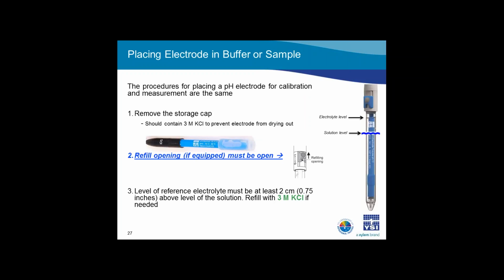When placing a sensor in either a buffer for calibration or a sample for measurement, make sure you first remove the storage cap from the tip of the sensor. The storage cap is provided for storing the electrode during shipment and long-term storage. I consider anything 3 weeks or longer to be long-term storage. For field probes, we'll talk about storage of lab probes shortly. The storage cap is filled with solution to keep the electrode from drying out and to slow the outflow of electrolyte. The solution used varies by manufacturer and electrode, but is usually KCl solution, buffer 4, or a mix of the two.